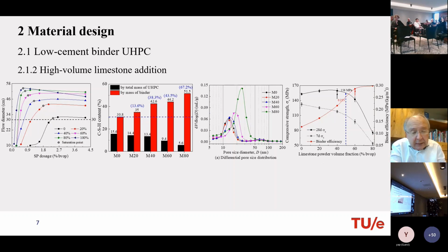We also look at limestone as a candidate for cement substitution, and you can see in the flow experiments, we look at the SP dosage, and we also did a test with zero cement to look at what limestone powder is doing in a spread flow test as a function of SP dosage. And you can see that the SP also interacts with the limestone. This is 0% limestone, and here we can see 100% cement, and you can see the mixes.